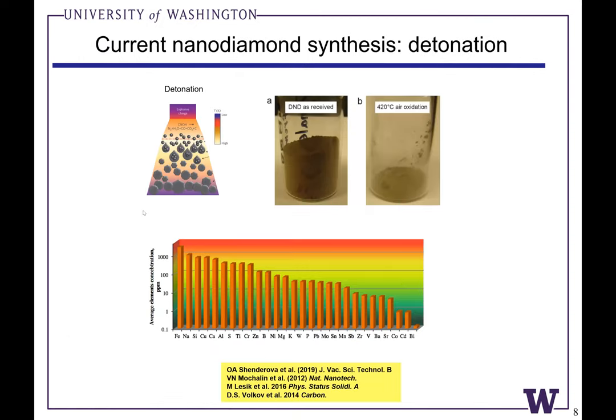But as I alluded to, the current state of the art is detonation synthesis, and this is a really extreme process. Following detonation, these impurities are very difficult to get rid of, and there are some very clever ways to detect them. Neutron activation analysis, there's some really nice work from Olga Shenderova and colleagues using neutron activation analysis to look at the distribution of heavy metals in nanodiamonds, and you can see parts per million, parts per thousand level impurities in detonation nanodiamond materials. This is what they look like after the detonation.